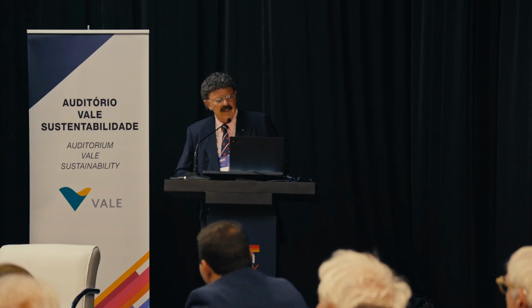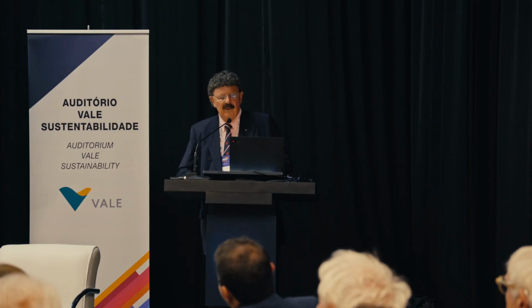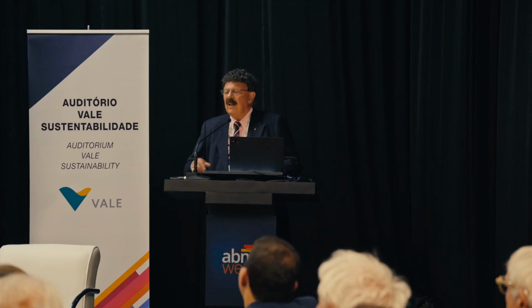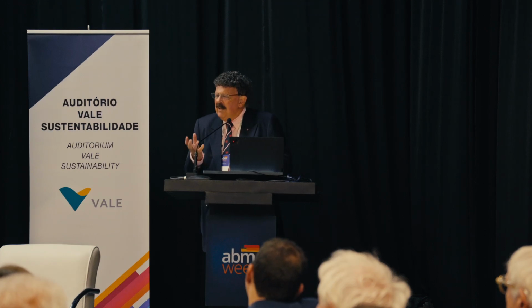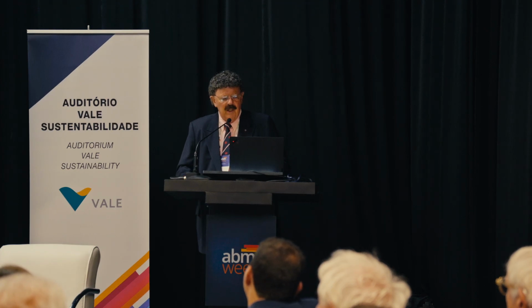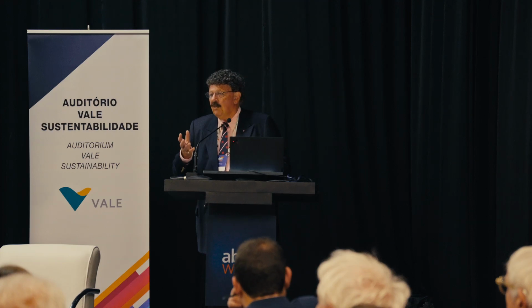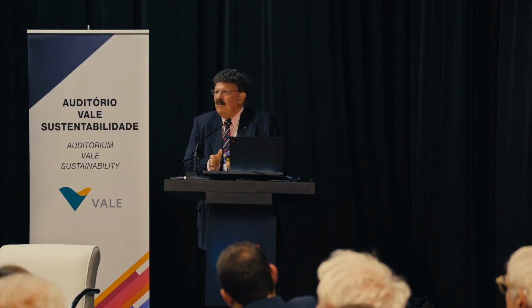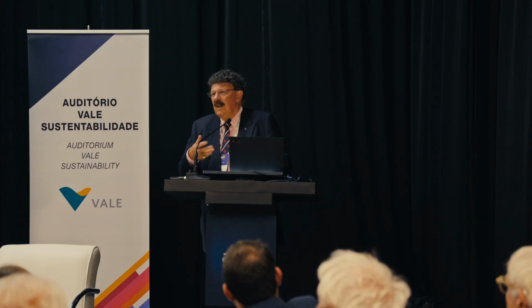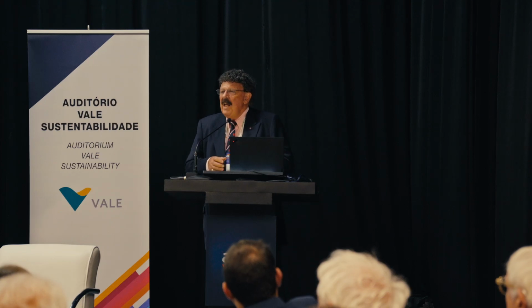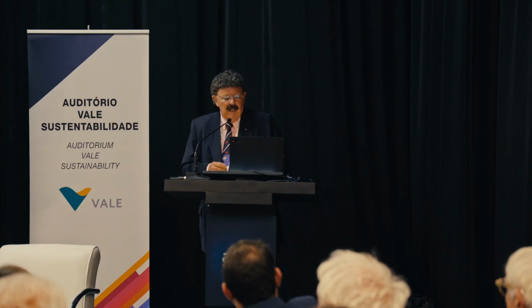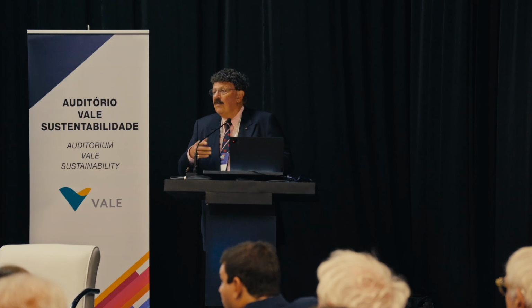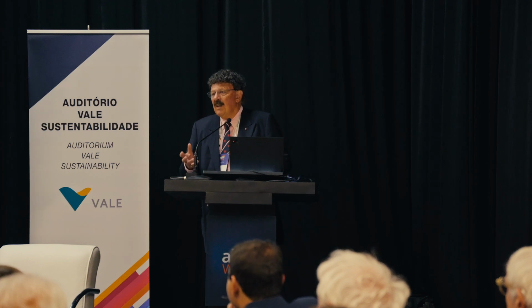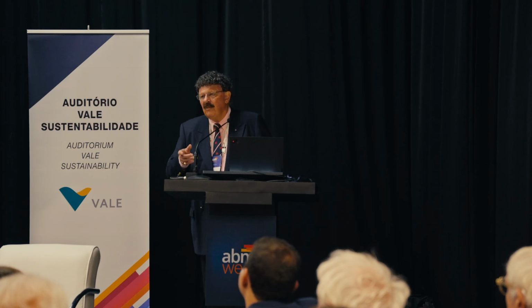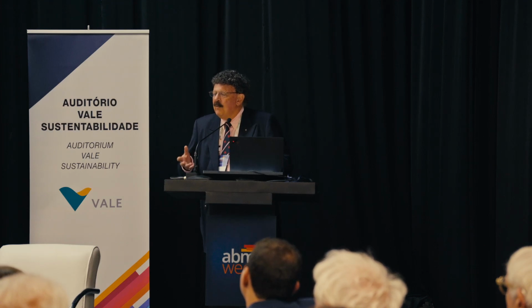You can see how the hardening becomes greater at lower temperatures. And the reason for that is a sequence of mechanisms. It's an unusual sequence of mechanisms, but it involves dislocation motion. It involves the formation of stacking faults, which would be the dissociation of dislocations. It involves twinning, and it involves the formation of another phase, a phase transformation. And at higher strain rates, as Mark showed, you can see it becomes amorphous as well.